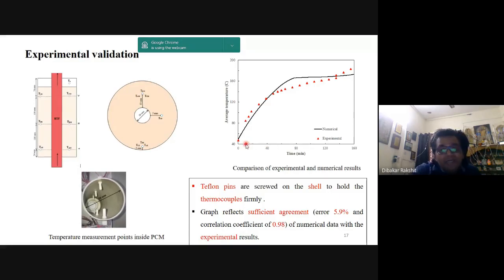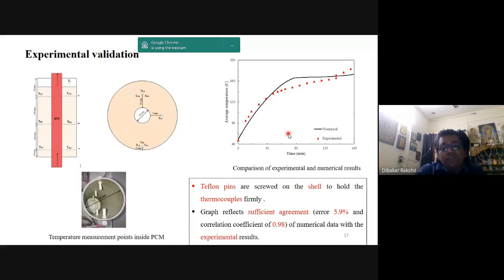So we compared it with the numerical data, the average temperature, the bulk temperature, which we obtained from all these thermocouples, and whatever we have modeled through our CFD analysis matched well with the experimental values obtained from this particular system, within an agreement of around 6% maximum error and a coefficient of correlation of 0.98.